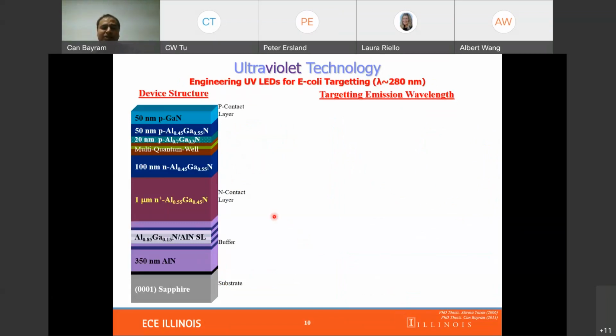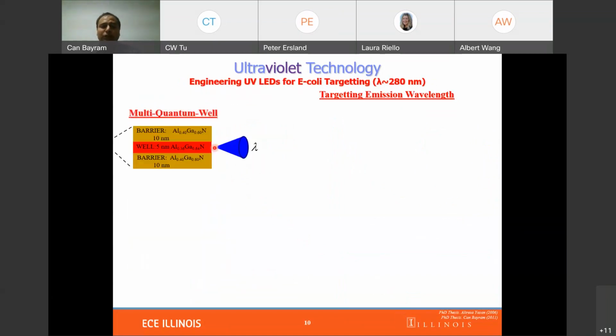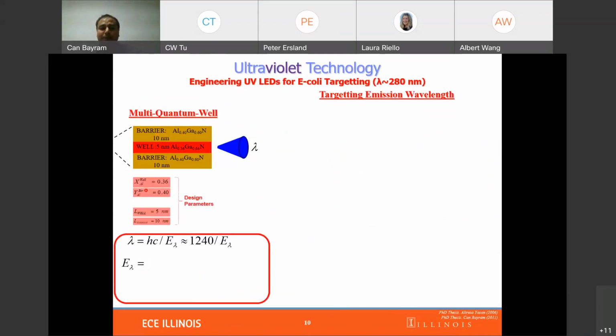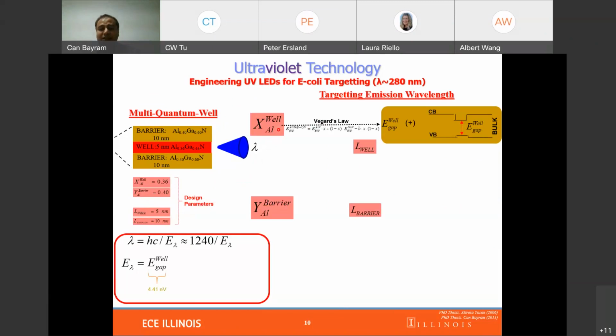So a UV LED structure is shown here. And of course, this is basically a PIN structure on a substrate, and we have lots of buffer layers to engineer and reduce the defect densities, but mainly the emission is coming from the multi-quantum well. So let's take a closer look. A multi-quantum well is basically a barrier sandwiching a well. So we have parameters such as aluminum content of the well and barrier and thickness of the well and barrier controlling our primary design.